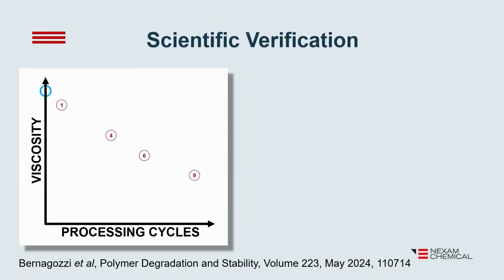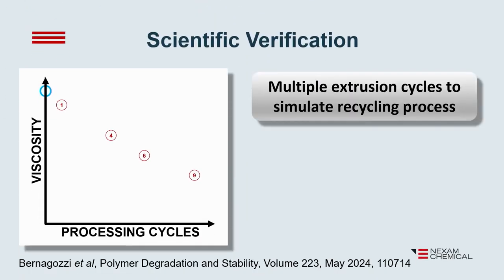But how does this really work? Let me show you some examples from a scientific study done by a research group in Italy. So what they did was they took a fresh polymer, and then they simulated what happens during recycling, and they basically put it into an extruder multiple times. So they take the material, put it back in, and back in. And what happened is that you see the viscosity decrease as you increase the number of processing cycles.